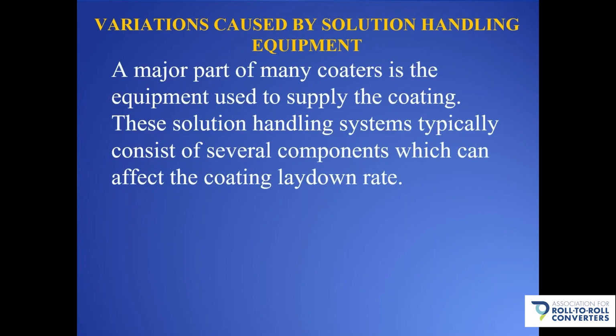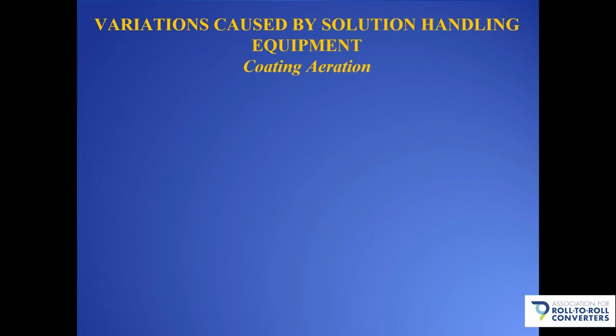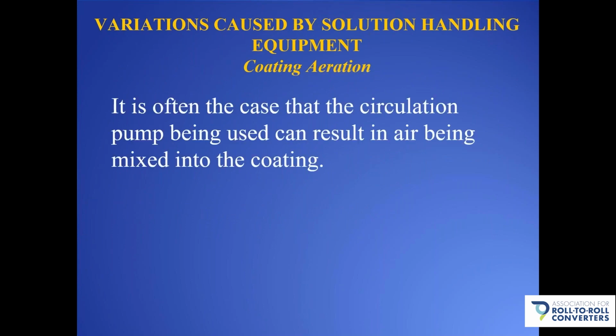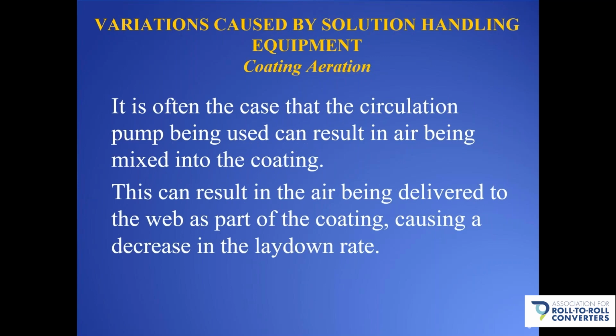So now let's move on to variations caused by solution handling equipment. A major part of many coaters is the equipment used to supply the coating to the coater. These solution handling systems typically consist of several components which can affect the coating laydown rate. Let's talk about a few examples of this. Let's start with coating aeration. It's often the case that the circulation pump being used can result in air being mixed into the coating. And this can result in the air being delivered to the web as part of the coating, which would obviously cause a decrease in the laydown rate.